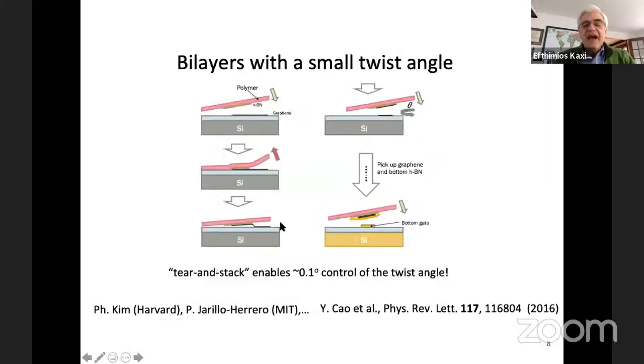So they actually have, here you see they have a hexagonal boron nitride on a smooth substrate. Hexagonal boron nitride is very stiff and very flat, and they stick that on top of graphene. Then they tear up half of the graphene and move it over and put it on top of the other. And on the bottom, they have another layer of hexagonal boron nitride. And it's this sandwich, the hexagonal boron nitride, very flat layers on the substrate that keep everything else completely flat. Very good point, but that's how they manage to do that.